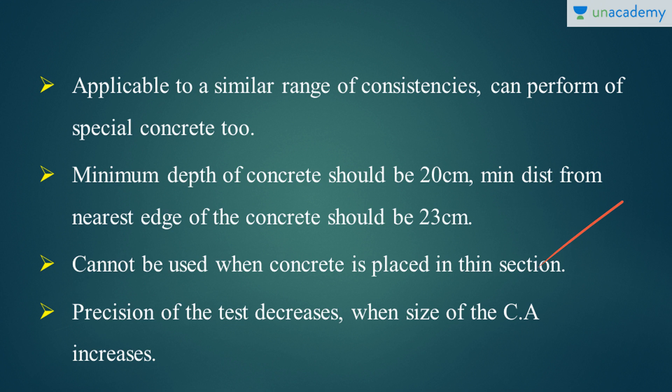If the concrete thickness is thinner than 20 centimeters, this test does not give any result. Also, if the size of the coarse aggregates increases, the precision of the test decreases — meaning it does not provide precise information when the coarse aggregate size increases. These were the two major drawbacks that prevented the Kelly Ball test from being adopted into the Indian standard.